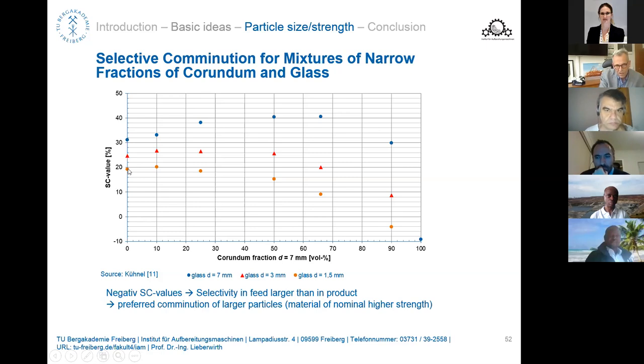You can see here that even here we have a small, slight increase only at the very beginning, with the first glass beads being poured into the mixture. From that point onward, the glass beads are less and less broken. So essentially, we see that even the glass itself should have less competency, but the size of the beads is smaller, and with the size effect, the strength again becomes comparable to the corundum beads.